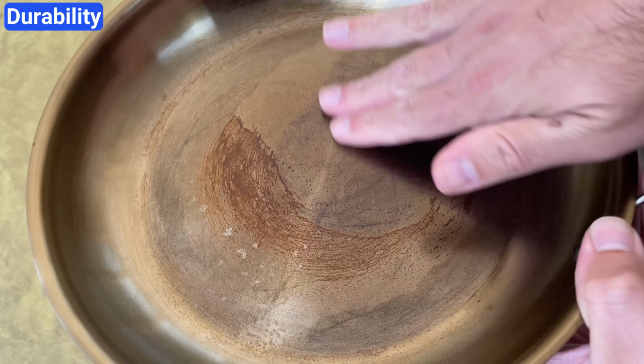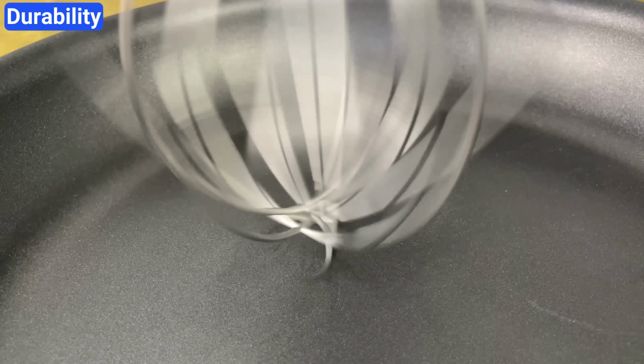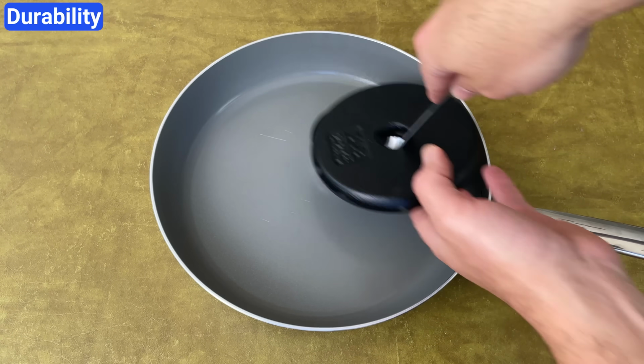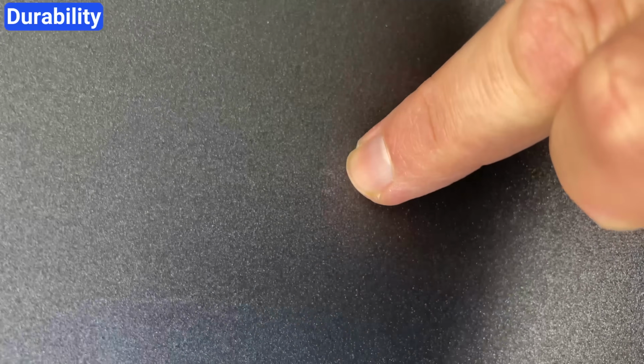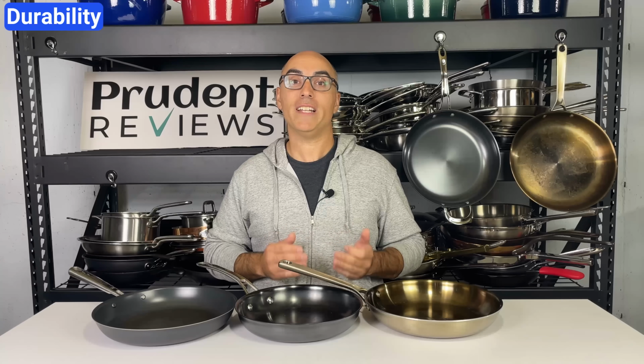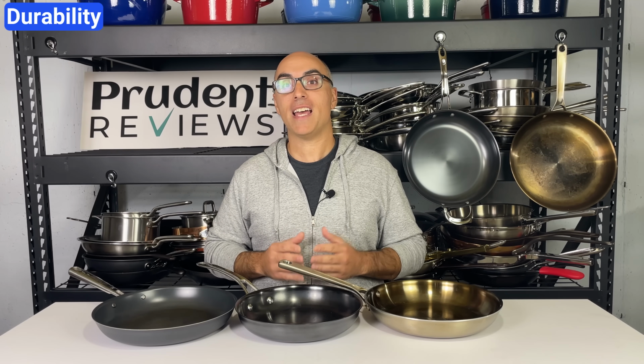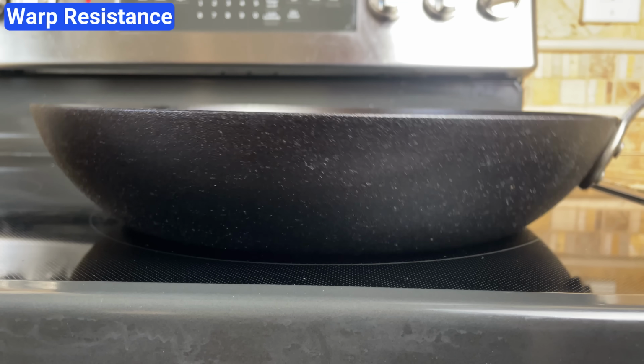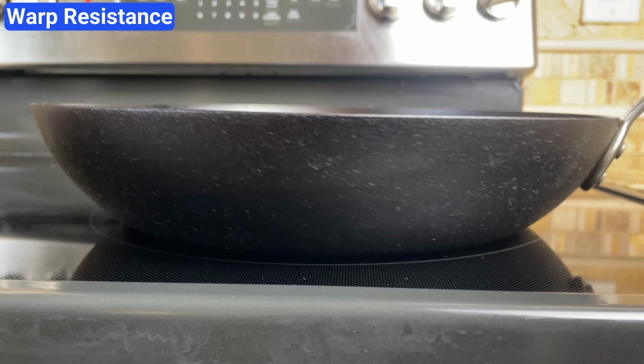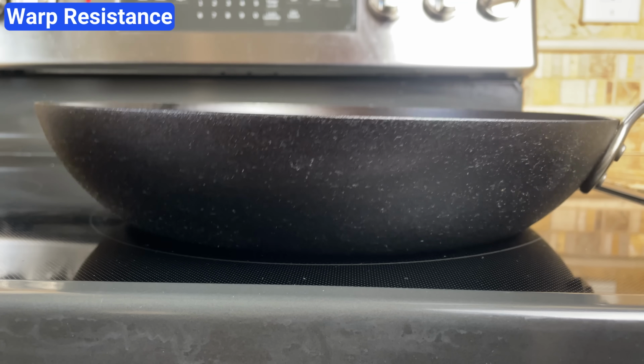For comparison, I ran the same tests on a Teflon-coated pan, a ceramic nonstick pan, and a hex-clad pan. All 3 of those ended up with visible scratches or coating damage. I'll show you a little later in this video whether those scuff marks had any real impact on the nonstick performance. Warping is another concern with carbon steel pans like these, especially on induction cooktops that heat extremely fast.